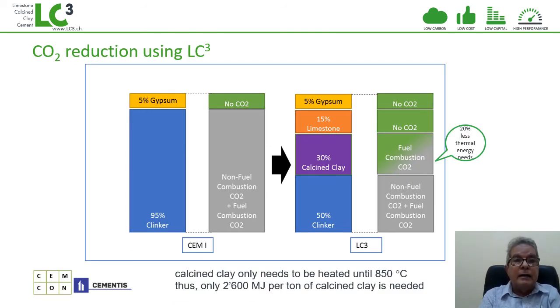In terms of CO2 reduction, here again, as I said, we're calcining the clay, but the clay does not emit any CO2 during calcination because it has no limestone. Meaning the CO2 associated with calcination of clay is only the one from the fuel. And we're dramatically reducing the clinker content, and clinker is the main contributor to CO2 emissions because of the decarbonation of the limestone in the clinker. So there's a lot of possibilities here by using these systems at 50% clinker, 30% calcined clay, 15% limestone to make a significant contribution to reducing carbon emissions, as I said before.